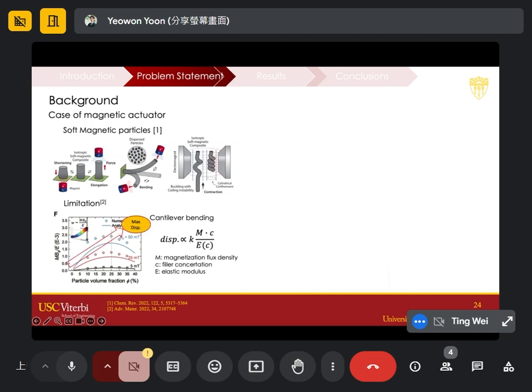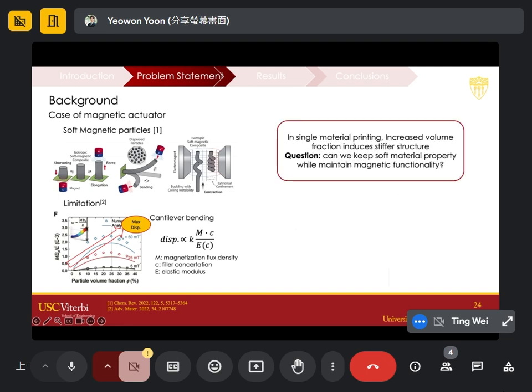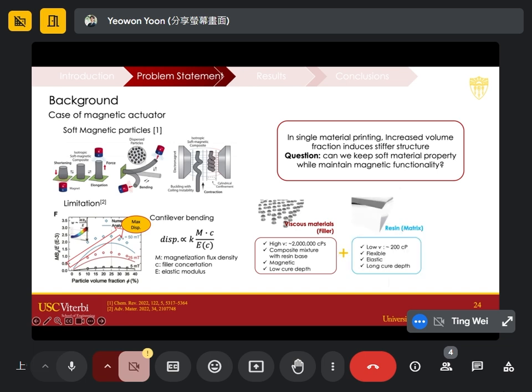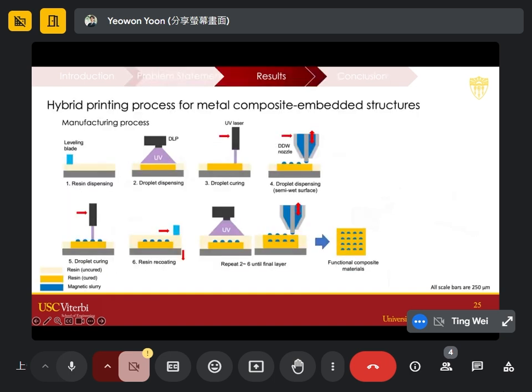Now, how about if we can approach this in a way that if you increase the volume fraction, we still achieve a maximum deflection? So the question we came up with is, can we keep the material soft while maintaining the magnetic functionality with a high volume fraction? Here, I suggest a way to do this: we print the viscous material that carries the functionality, which is the filler material, at about 2000 Pascal second. And then we still print the main housing using resin printing. So we can selectively deposit functional, here magnetic, particles within a resin matrix. This is the process we came up with.